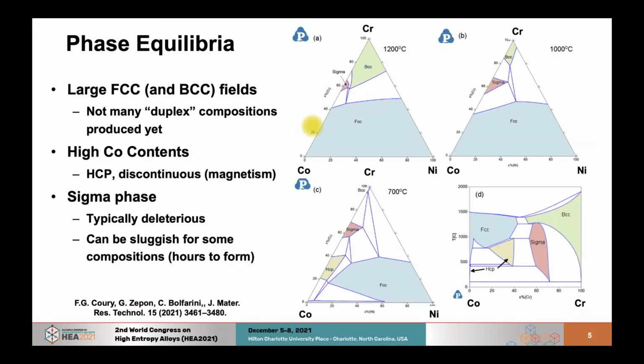So just a brief overview of the phase equilibrium of the system. For chrome contents from 40 to 50%, we display a large FCC single phase field, especially at high temperatures. By decreasing the temperature, we start seeing the chrome-rich phases, which are the BCC and sigma. Sigma is more on the chrome cobalt side. The phase fields where they are stable grow. And at even lower temperatures on the cobalt chrome side, the HCP phase forms.